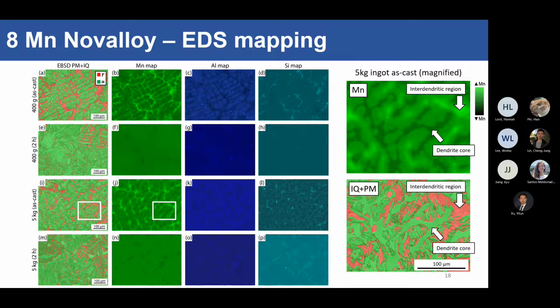Right, okay, so now we homogenize it for 2 hours. Now let's take a look at what happens. So this is your manganese map, aluminium and silicon map of the 2-hour homogenized one, for the small and the big ingot. You can see that there's still a bit of manganese depleted regions, and that corresponds to your delta ferrite that you just couldn't get rid of. But the rest of the matrix, the rest of the microstructure, looks pretty homogeneous, right? It's quite a nice uniform shade of green.